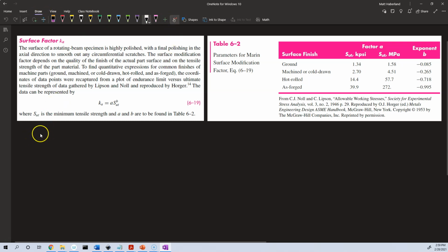Let's write down a little bit of information about our problem. SUT for our steel is 150 KSI. And the first thing that we wanted to know: what is Se prime? What is the endurance limit of a perfectly polished specimen? All that we're given is the ultimate tensile strength of the steel. Now, we've already covered in earlier parts of the preparation that we can estimate the endurance limit of a perfectly polished specimen as 0.5 times the ultimate tensile strength of the material. So in our case, we have 75 KSI is what we'd expect our specimen to survive for an infinite number of cycles. That's the endurance limit of a perfectly polished specimen. That was the first part of the problem.